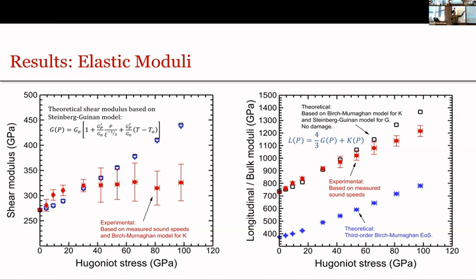First of all, if we look at the low stress data, the measured shear modulus is larger than the theoretical value. This is because at the shocked state, the microstructure is consolidated under compression, which makes the shear modulus go higher. And as the peak stress goes higher, the microstructure will be accompanied by micro-cracking and fragmentation, like material damage, which will lower the shear modulus, which is also not accounted for by the theoretical model. And that's why we see this big discrepancy.